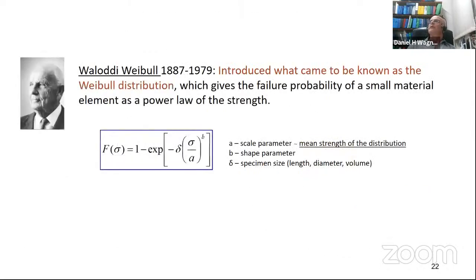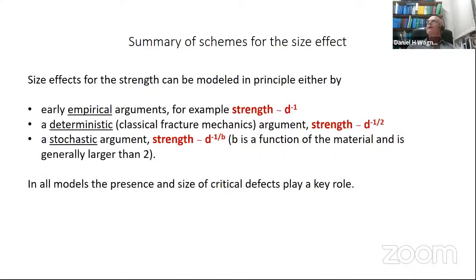Then we have Weibull, who introduced a probability distribution and the size effect. And the size effect in this case gives the scaling law that goes as diameter to the minus 1 over b, where b is a shape parameter, and a is a scale parameter, which actually is nothing else than the mean strength of the distribution. So the schemes are empirical.